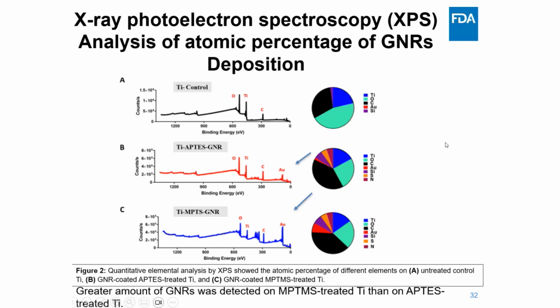Also next, to confirm what elements were actually present on the surface, we used a technique called X-ray photoelectron spectroscopy, or XPS. This is a surface sensitive technique that detects elements within just a few nanometers of the surface. Both APTES and MPTMS coated samples showed the presence of gold, but the MPTMS treated surface produced a noticeably stronger gold signal, indicating more efficient and stable nanorod attachment.